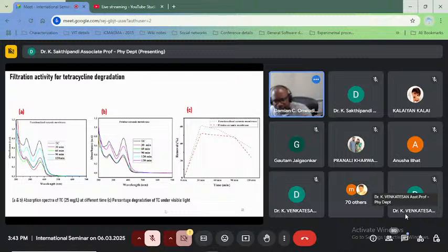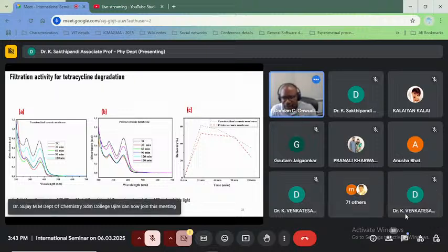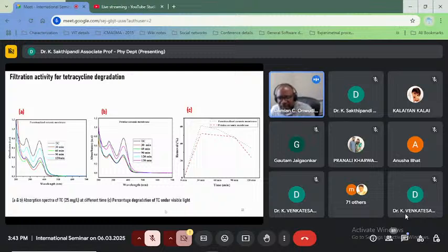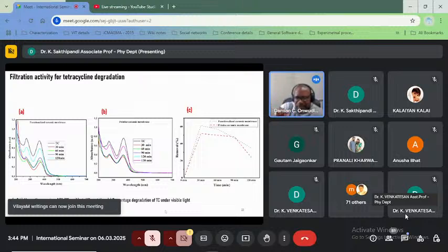In figure C on my right, we checked the efficiency of the pristine ceramic membrane and that of the functionalized ceramic membrane to check what the difference is. Why do we have to pass through this whole process if no effective difference is registered? And we found out that the black dots in graph C on my right show the efficiency of the functionalized ceramic membrane after 2 hours, and the red line is that of the pristine ceramic membrane after 2 hours. So we can see that the efficiency of the functionalized membrane was higher than that of the pristine ceramic membrane.